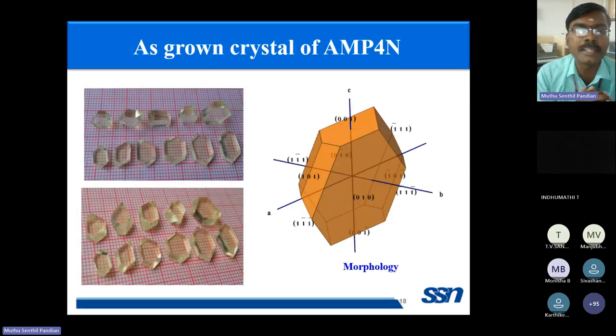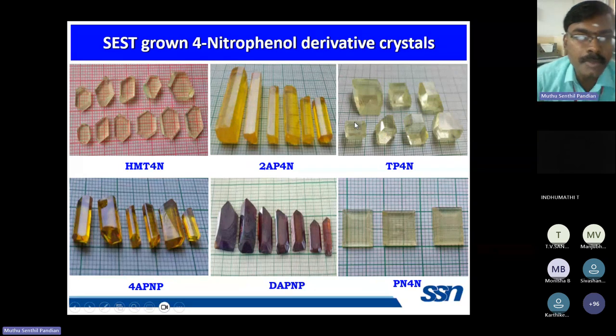So this is one more example, AMP4N, one more 4-nitrophenol derivative single crystal. This is a crystal grown by the conventional method. This is the morphology. For this unidirectional solution crystallization method, we have selected this fast growth axis, the 001 direction, for the bulk growth. So these are some of the conventional method grown 4-nitrophenol derivative single crystals for nonlinear optical application.